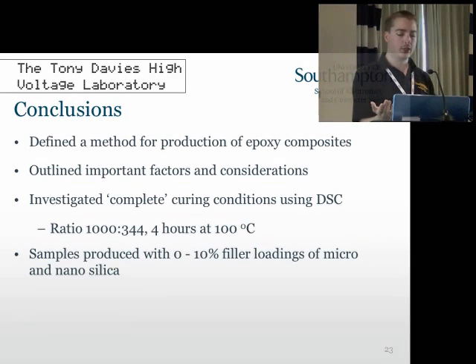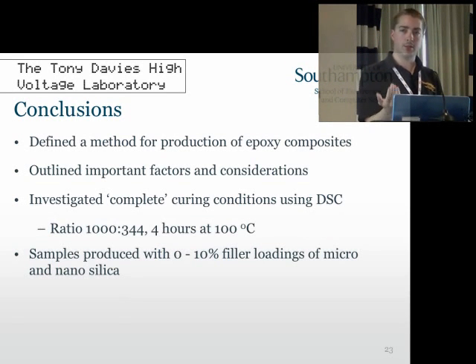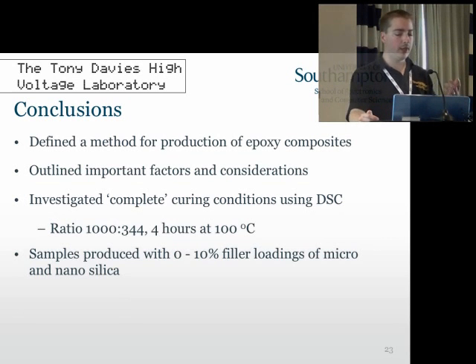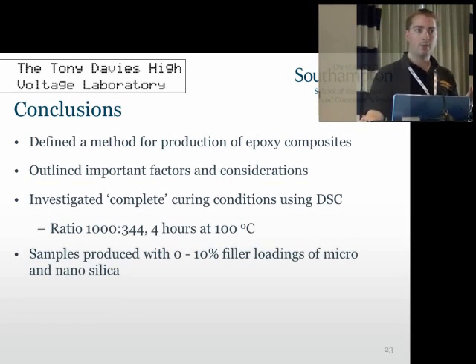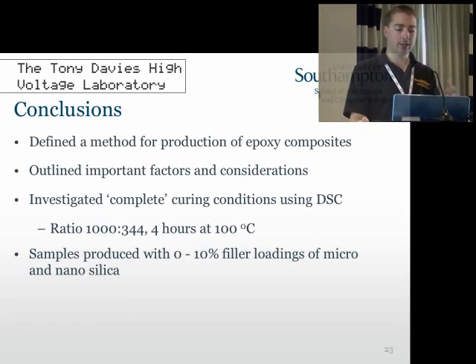And then we've produced samples with 0 to 10% of the micro and the nano fillers, just to give us an idea of how an easily created filled system would respond. So we haven't aimed to disperse the filler perfectly. The main aim is simply to see how easily we could get it in there and the effects that it would have.